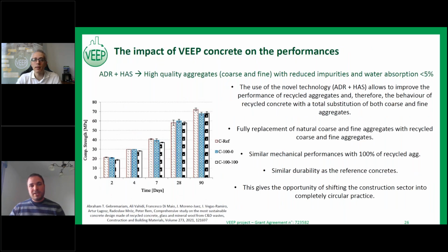Okay, so in a second stage, we tried to demonstrate the effect of both fine and coarse recycled aggregate in new eco concrete. For the study, we have manufactured different combinations of new concrete, increasing the percentage of recycled aggregate, arriving up to 100% of recycled material, and also including the eco-cement studied in the previous stage. With that, we arrived at a total substitution of 100% by weight of natural material with recycled material.